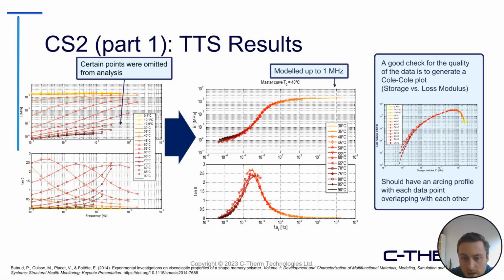On the right here, a good check to always see if your TTS data checks out is to do a Cole-Cole plot where you plot the storage versus the loss modulus. You should get an arcing profile with each data point overlapping with each other as we see here. So I suspect the points on the right plot were ignored or omitted because they didn't follow this ideal profile.